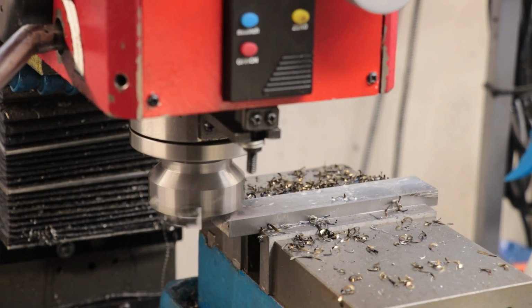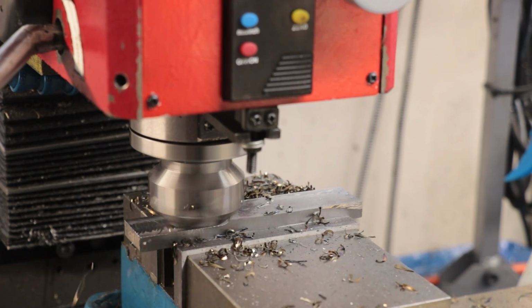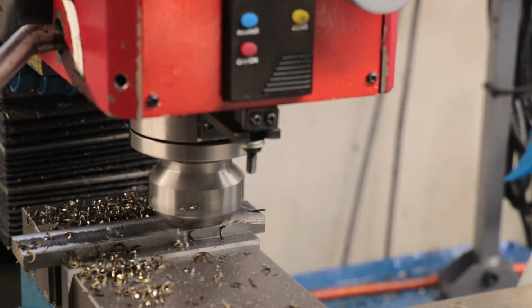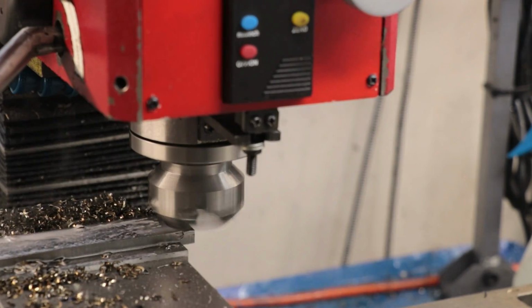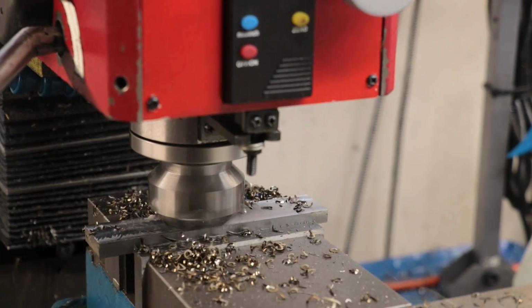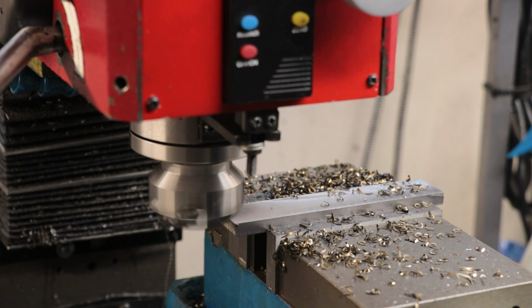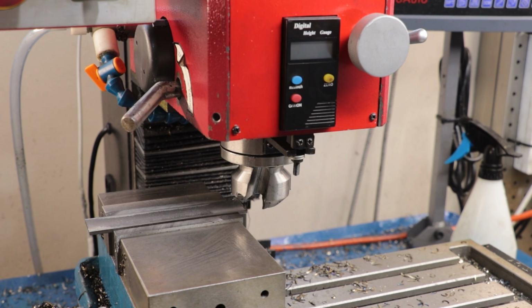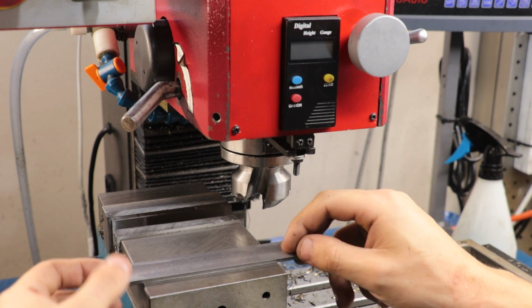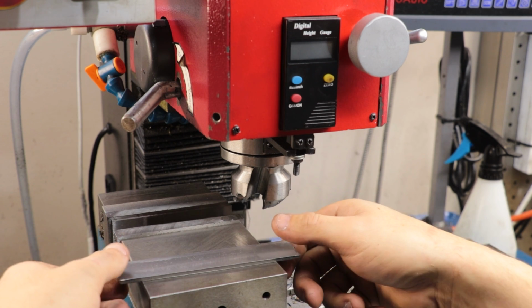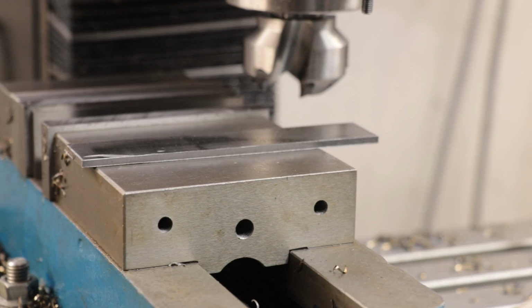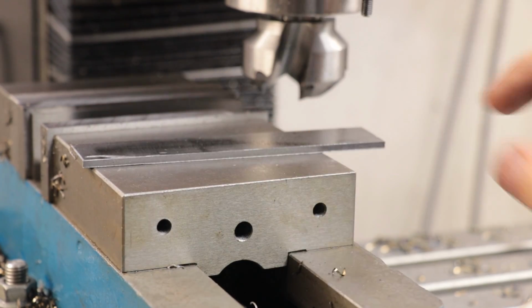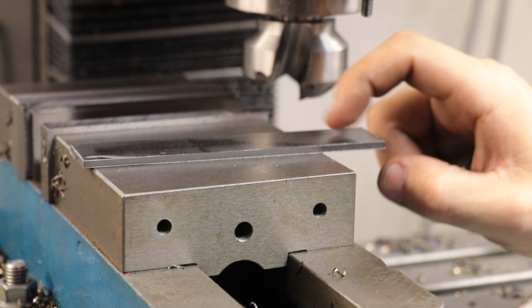As an example, I'm going to be machining down a piece of cold rolled plate, and I'm going to be taking all of the material away from one side only. In doing so, that should leave the internal stresses sort of unbalanced, so to speak. Now I know that the mill should be adequately trammed, so the piece should be perfectly flat whilst it's still in the vise, but once I take it out of the vise, you can see that it's no longer flat. The stress in the steel has warped it.